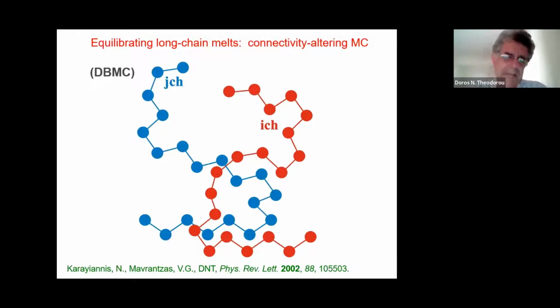We said molecular dynamics cannot reach the times that are relevant in these melts. For a very long time in our group, we have been developing Monte Carlo methods to fully equilibrate polymer melts of very long chains. And these employ moves which change the connectivity among the polymer chains. An example is the so-called double bridging Monte Carlo move.